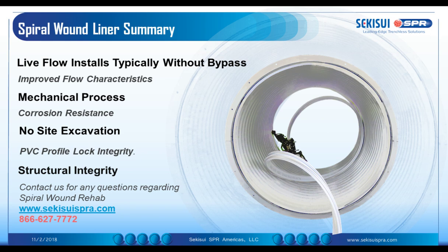Right. At the beginning of the presentation, you mentioned the lifespan is generally designed to be 50 years. Is it possible to have a liner designed and tested for a 75 to 100-year lifespan? Absolutely. One important clarification is design life and service life. The design life comes into the structural design, in which case we typically use an effective 50-year long-term stiffness. We have done the long-term testing according to ISO methods, according to the ISO standard. Now, that's typically out to 50 years, but the data can, with a sufficient degree of correlation, be extended out further. We have, for example, I do recall, had one design where it required an 80-year design life as part of the design. And so, yes, that can be readily done. It just requires a further extrapolation of that creep test data.